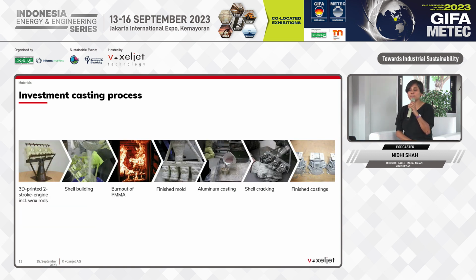A quick look at the investment casting process with 3D printed patterns. So you would ideally 3D print a pattern from the CAD data, then go through the shelling and the burnout process as you would in your regular foundry process, and have the finished mold. You would autoclave or burn out the pattern and pour the casting. As you can see, this eliminates the need to make a tool or a die for the wax patterns, which is a big advantage with 3D printing. A quick look at the process video.